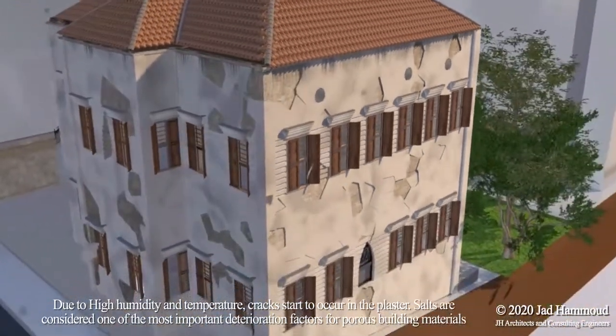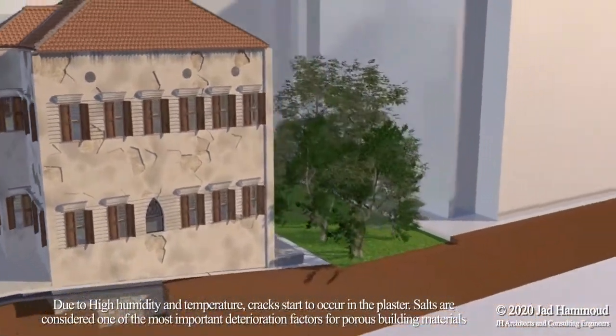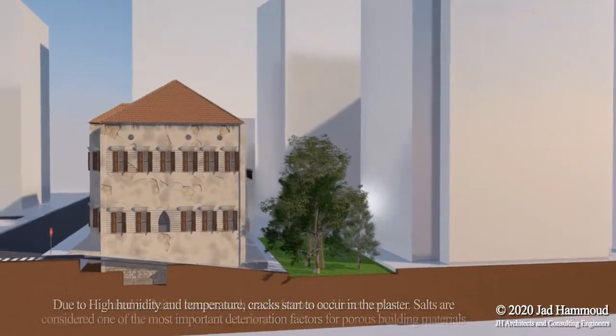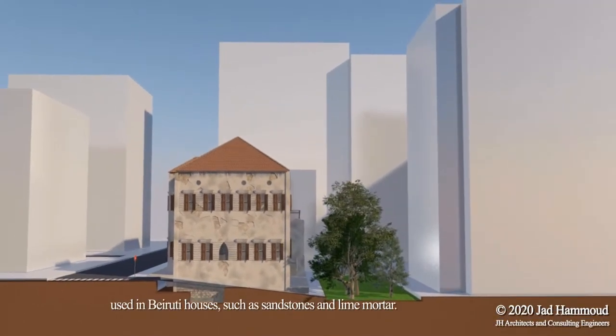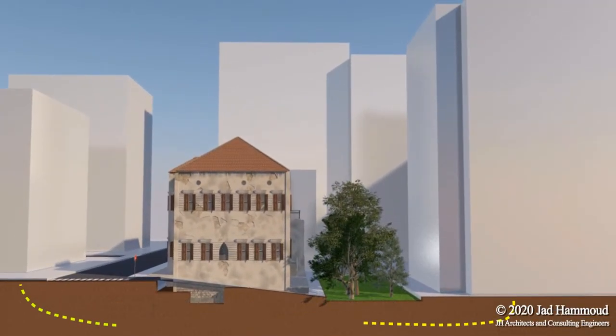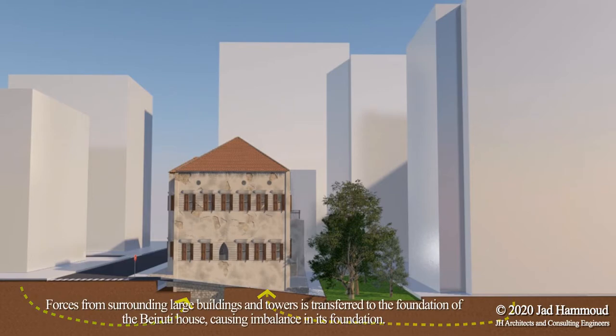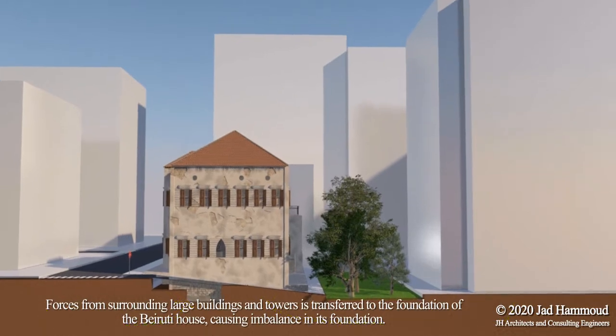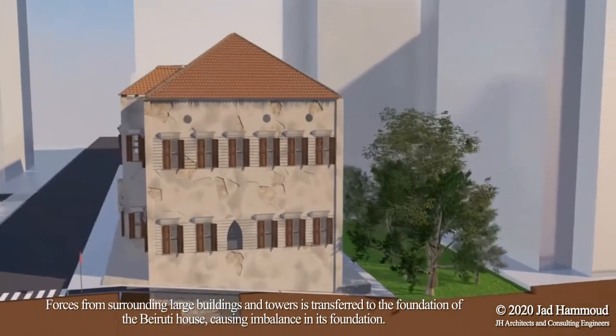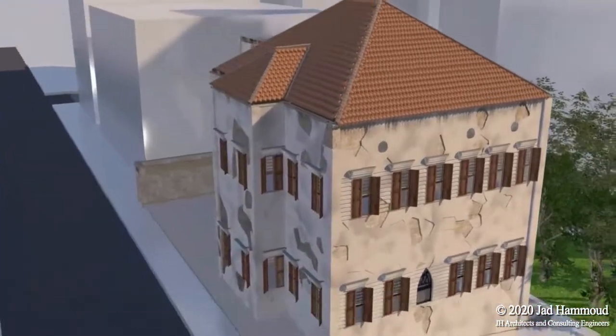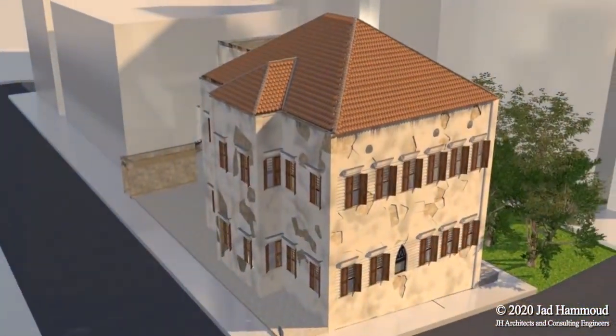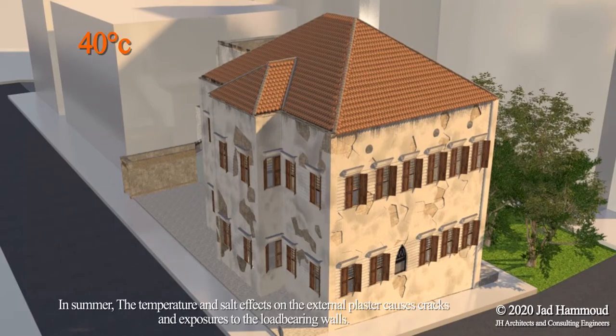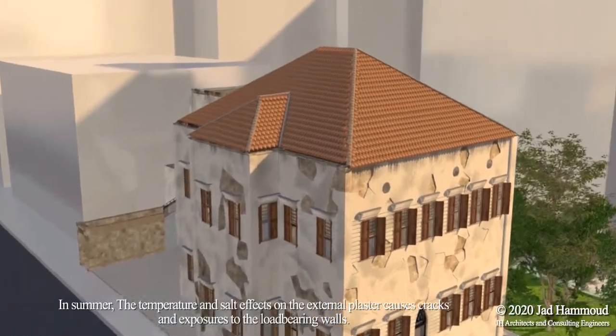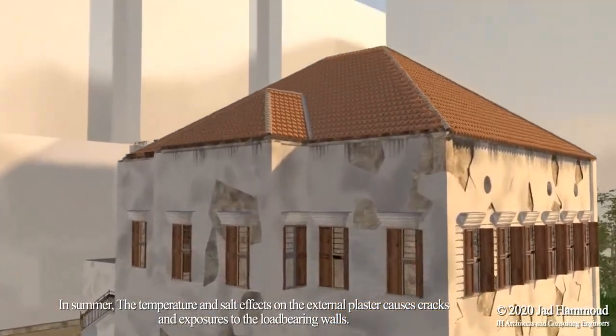Salts are considered one of the most important deterioration factors for porous building materials used in Beiruti houses, such as sandstones and lime mortar. Forces from surrounding large buildings and towers are transferred to the foundation of the Beiruti house, causing imbalance in its foundation. In summer, the temperature and salt effects on the external plaster cause cracks and exposures to the load-bearing walls.